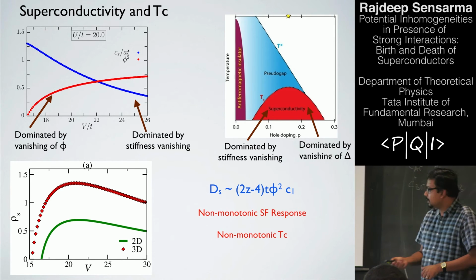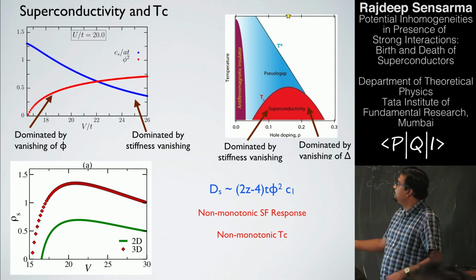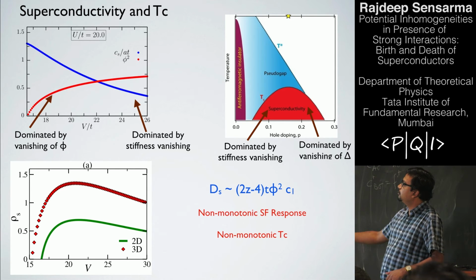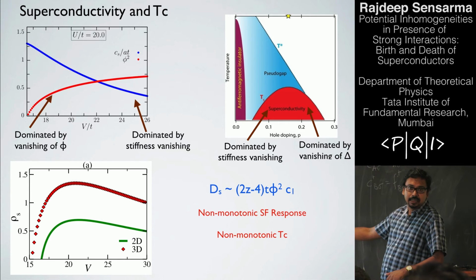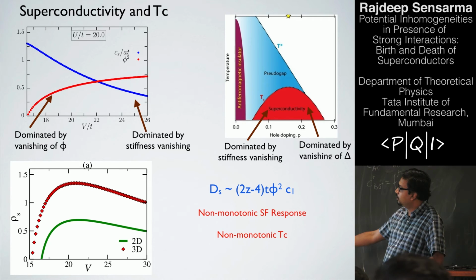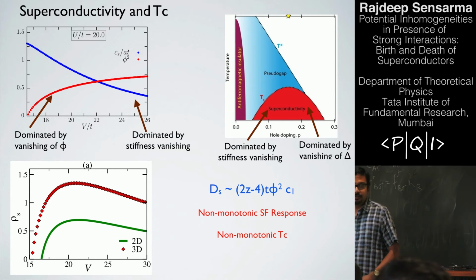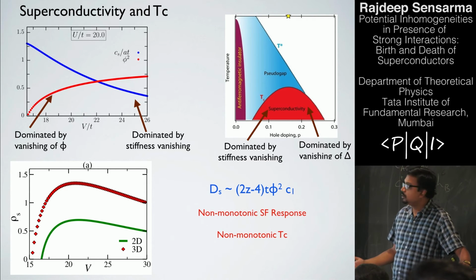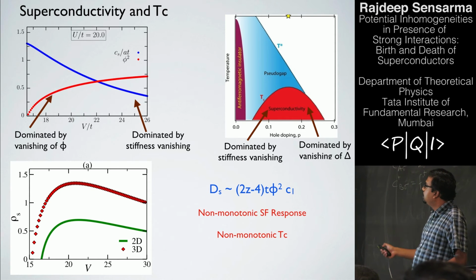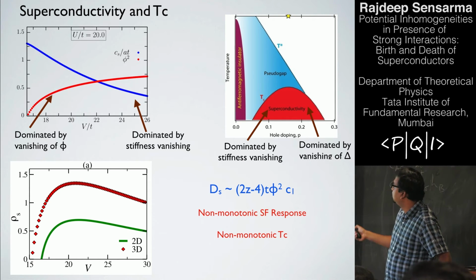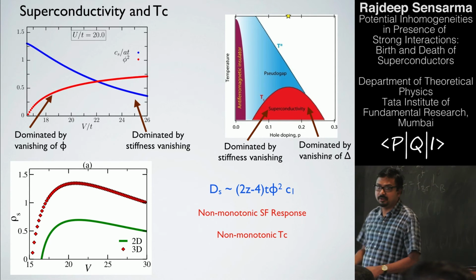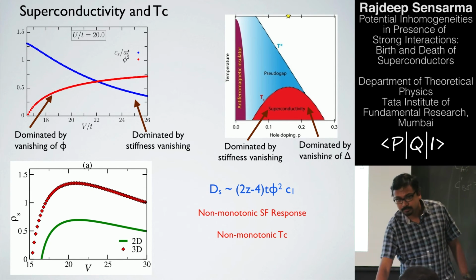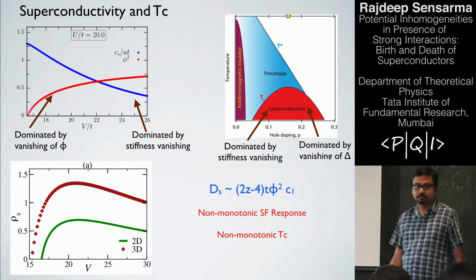So what happens is that since it's proportional to phi square and C1, phi square of course increases as a function of V. C1, the number of singlets, goes down, and so the whole thing looks like a non-monotonic dependence on V. It reminds you of high Tc, where there is again a non-monotonic dependence of Tc on some parameter, in this case dominated by vanishing of the order parameter, and in this case dominated by vanishing of the stiffness. So for 2D I can understand why stiffness is related to Tc.